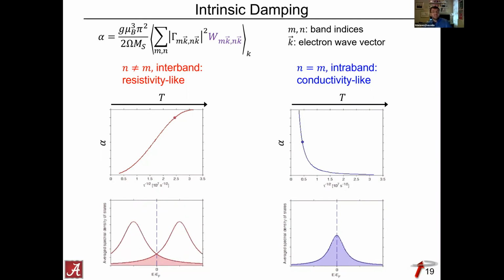What happens here is as you lower the temperature, as you can see here, the density of states at the Fermi level for this particular band that we're looking at increases, and therefore your damping parameter should increase as you decrease the temperature, and that will become important in just a little bit.